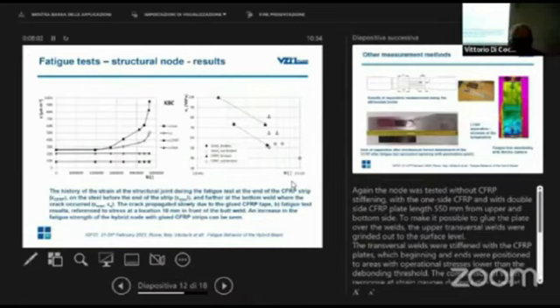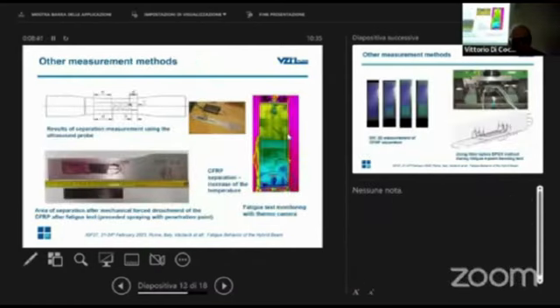And here is the evaluation of the fatigue test. On the left side, you can see the bottom two lines, there is stress before and on the CFRP plate. So the ends of the CFRP plates are not debonding, but they are forming cracks on the vertical welds, which are connected to hollow beams. And here are two SN curves. The left is without CFRP and the right is with CFRP.